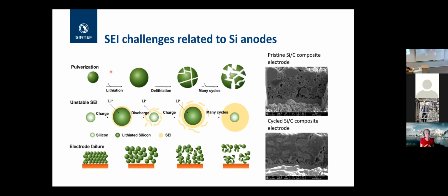When you take the lithium back out, the material will start cracking and you form new surfaces. Each time you form a new surface, new SEIs will form, and eventually you consume all your electrolyte. And you also have the problem of breaking up your particles, and you lose contact between your particles, and you lose contact with your current collector.